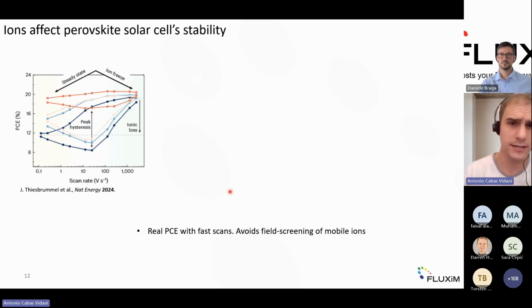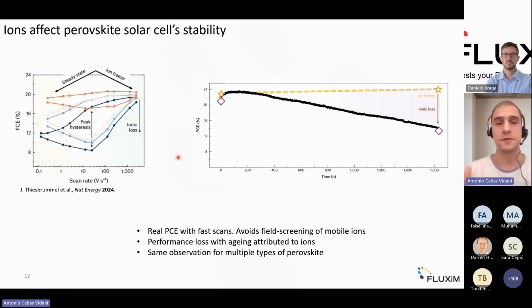Now, to do that, she performed JV scans in a wide range of scan rates, up to a scan rate of more than 1,000 volts per second. In this way, you reach a state where your ions are not moving. So this means that is the effective PCE, the effective performance of your device, assuming there are no mobile ions influencing your performance with a field screening effect. And she performed this kind of measurement also on degraded devices.